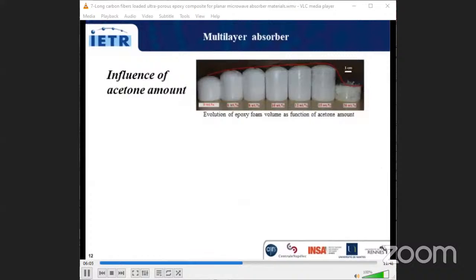Now I will present the influence of the acetone amount left in the resin on the structure of the foams. We can see clearly on this photo that the volume of the epoxy foam increases when the amount of acetone increases to 15%. After that, the limit is reached at 20% of acetone.